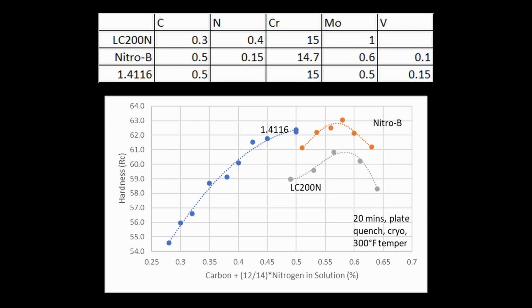And so I remember learning about this stuff and heat treating it, and why can't I get this stuff harder? I think the peak hardness I was ever able to get was like 62 something from the first temper, and then dropped it down to like 61 and a half for the final temper. That was the max hardness I could ever get this stuff to. And I was like, man, what's going on? Why doesn't this stuff get crazy hard? And I thought the explanation in the past was pretty solid that, okay, we have so much chromium in solution that we're limiting that hardness. And so I was like, well, dang it. It's just a huge trade-off for all of that corrosion resistance, all that chromium in solution. But from this work that you've done here, that's not the case.